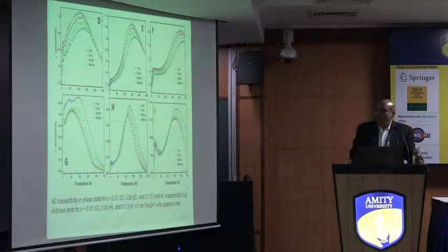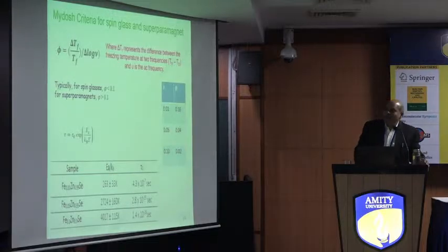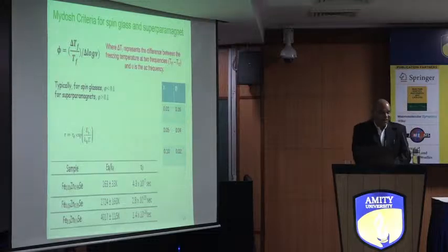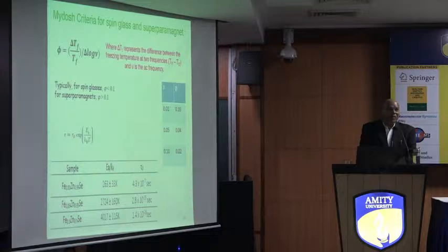And this is the AC SQUID. Then we take the chi double dash. Then you can see at 25K some transition is coming here. Then you can see it for higher concentration. By the help of the Mydosh criteria, we can say whether it is a spin glass or a superparamagnetic material.